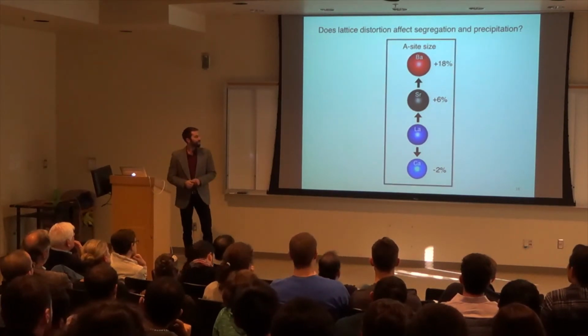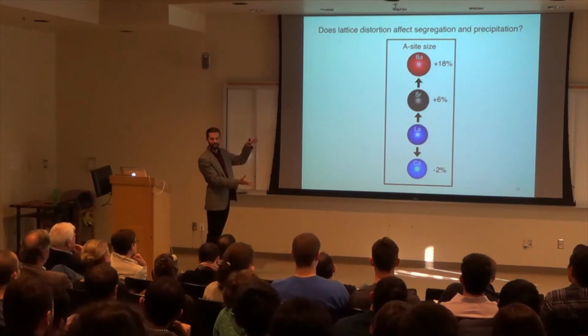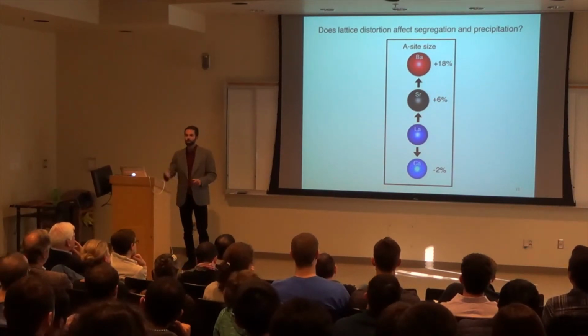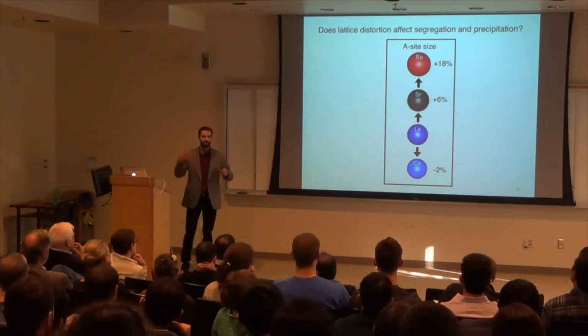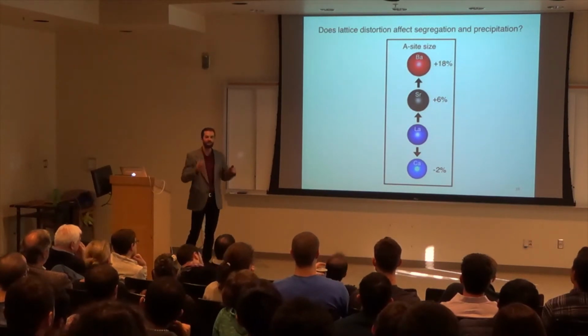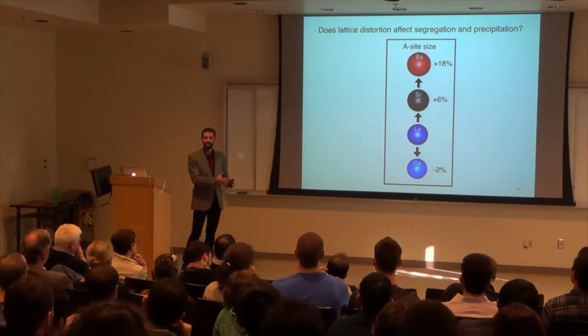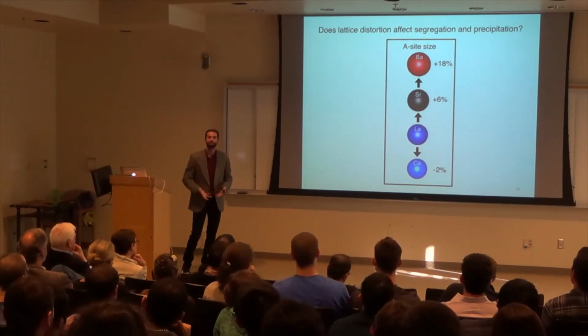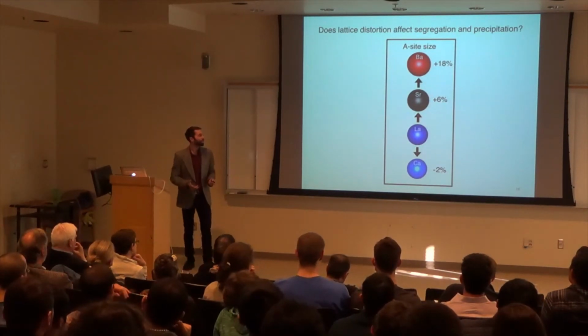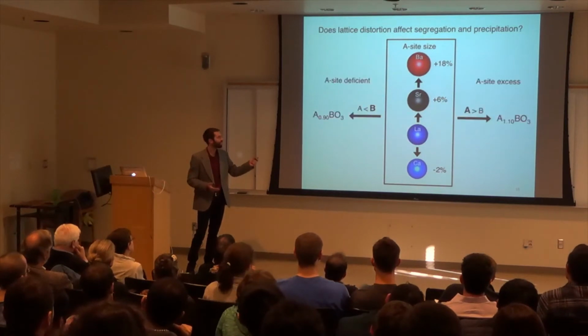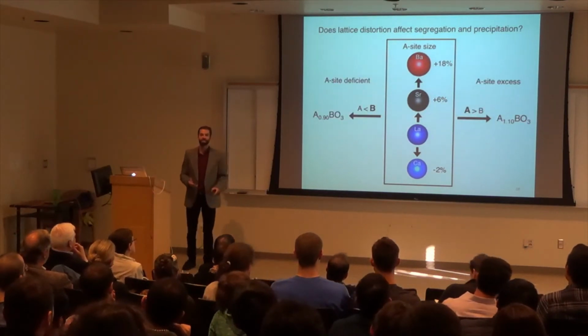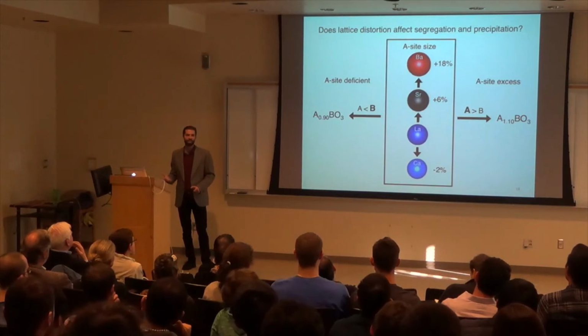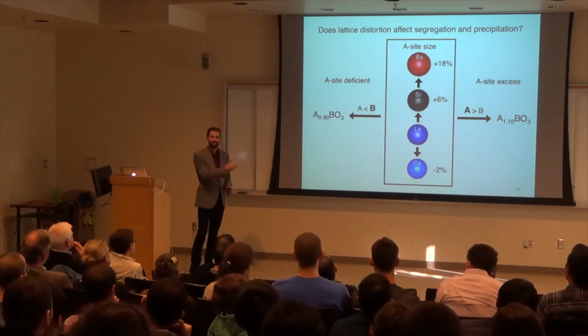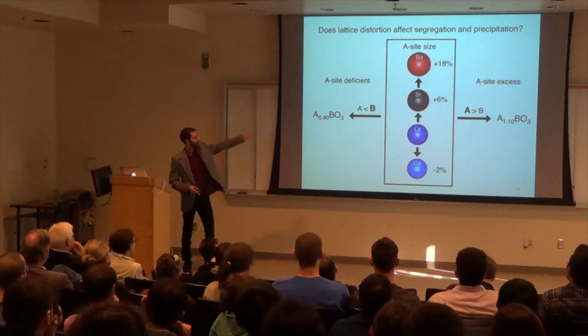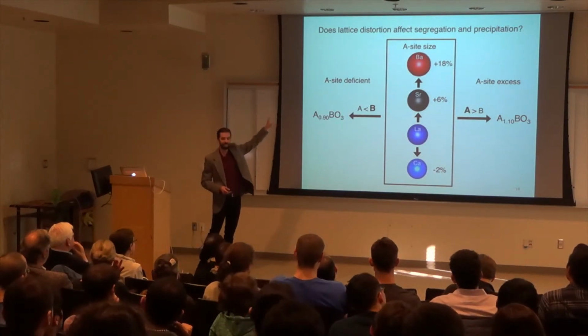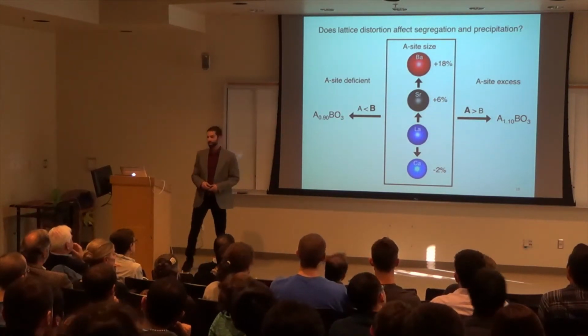Now, in addition to changing the A site size, what people have done to try to reduce precipitation, which is considered to be bad, is to just put less of the A site in the material, making it A site deficient, in hopes that it doesn't precipitate as much on the surface. So at the same time that we're studying A site deficiency, we're also going to study the A site excess to see, is there really a good reason not to put a lot of A site into the material? So we have changing the ionic size in the A site and putting less of it and more of the A site into the material.